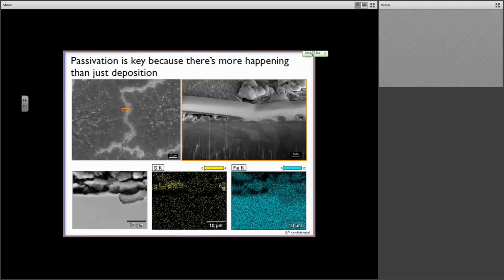So iron is being dissolved from the surface and reincorporated into these deposits, which strongly suggests that it's not just deposition that's happening here, we also have a corrosion mechanism that is active, and that corrosion mechanism actually may be accelerating and exacerbating the deposition process. All right, so basically what we're showing here, and I'm not going to go into all the details of this, but when we put the oxide on the surface, that effectively prevents the corrosion reaction from happening. So if we can stop the corrosion, we turn off much of the fouling behavior, especially at high temperatures.